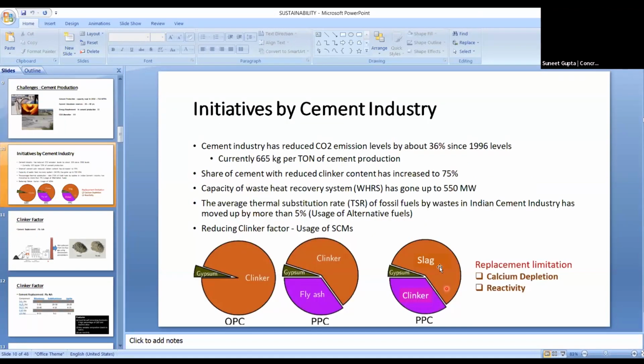Carbon dioxide, as I told you, we have gone down to 665 kg per ton from 900, 950 plus. The share of cement with reduced clinker has gone to more than 75%. Waste heat recovery systems in cement manufacturing have gone up to 550 megawatts. And reducing the clinker factor, yes, by using supplementary cementitious materials like fly ash and slag, which are generally considered wastes in thermal power stations, the power industry, and the steel industry, from where we get slag. They have been consumed and reused in cement manufacturing and made into useful products. Hence we have reduced the clinker from 90-95% to say 70-75%.